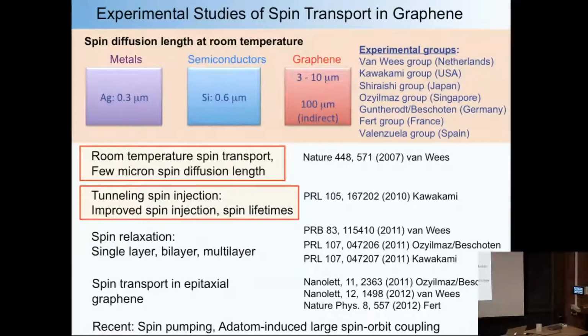And I just want to give you some sense about how the field developed. I mean, one thing I would say is that if you compare at room temperature the spin diffusion length, so this is how far electron spins will diffuse before they depolarize. If you look at metals, I think it's a little better than this now, but it's on the sub-micron level. Silicon at room temperature is up to 0.6 microns. I think that's improved a little bit. And graphene, I would say a reliable number is between 3 and 10 microns, although people have reported higher. People have reported as high as 100 microns, but I don't know if I trust that. But anyways, if you compare to the other materials, the spin diffusion lengths are really quite good.